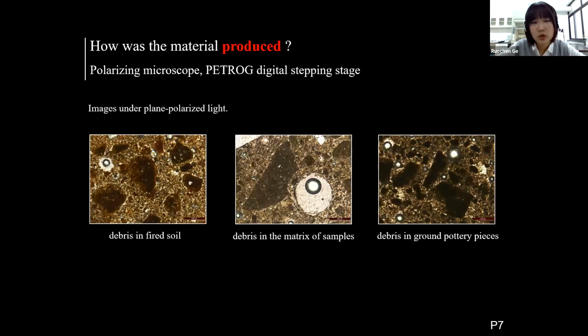Moreover, the samples show another interesting feature, that the debris in the matrix have obvious edges and corners, like the 2nd picture, while the debris in the fired soil, which was selected nearby the sample, are more round, reddish brown, and contain sand-sized inclusions, like the 1st picture. Therefore, we think that artificial grinding may be the only possibility for the formation of the debris in the samples.